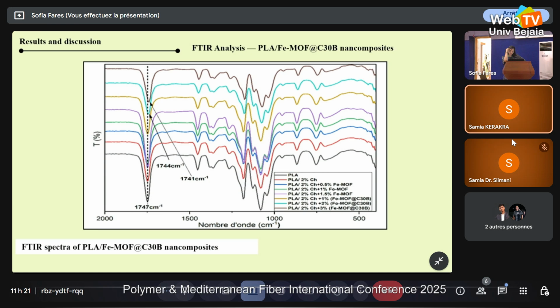Now let's see infrared analysis of our nanocomposites. Just slight shifts of the carbonyl stretching band from 1747 to 1741 were observed in the 2 and 3% composite formulations, and these shifts suggest weak interactions between the PLA matrix and pillars, likely through hydrogen bonding or similar interactions, like van der Waals interactions.